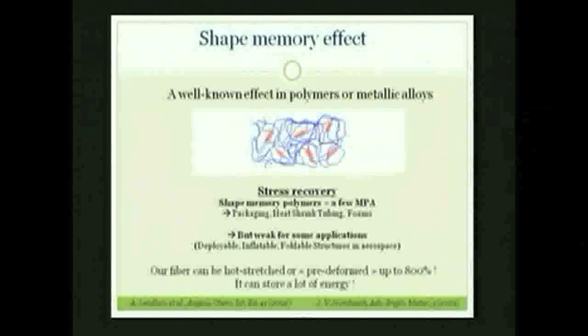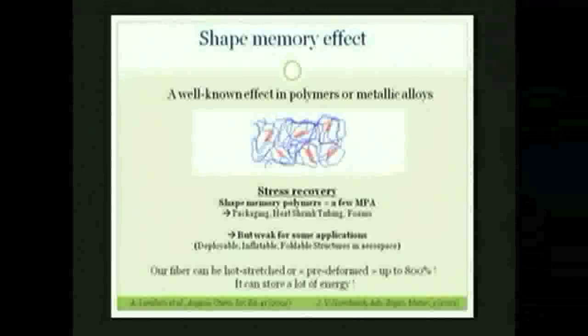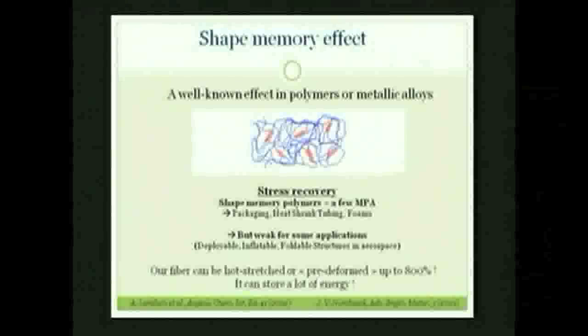Because the stress recovery is very small, it's too weak for some applications, especially, for example, in aerospace, where they aim for deployable, inflatable, foldable structures. So we were thinking that our fiber, because it can be hot-stretched or pre-deformed up to 800%, a lot of deformation, stores a lot of energy. And if it stores a lot of energy, maybe it can give back a lot of energy too. And maybe the shape memory effect will be very high.